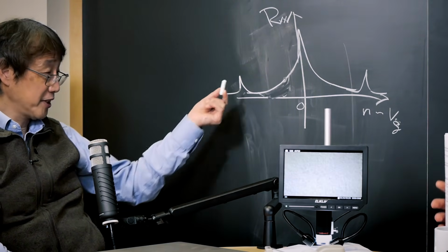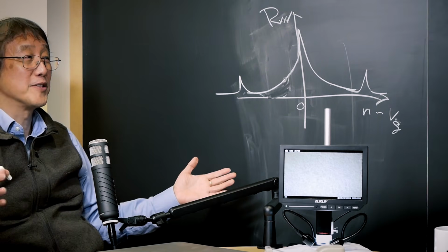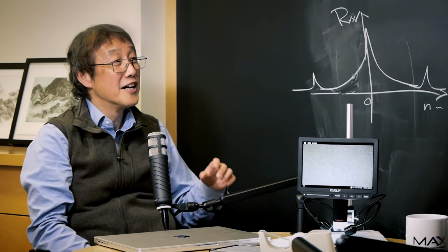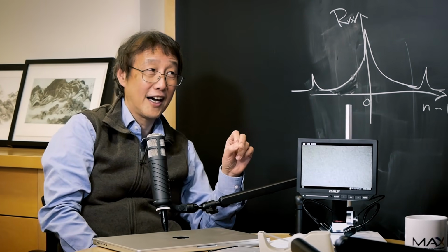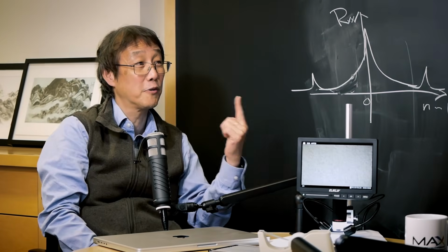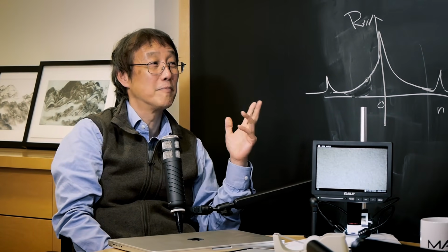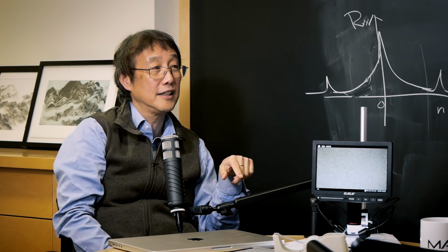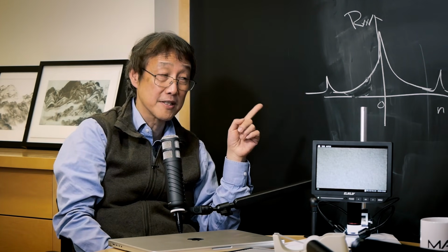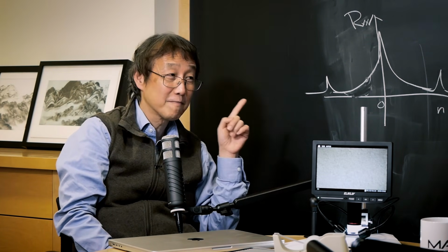But when you put this under a magnetic field and measure the quantum Hall effect, it is really complicated. Plateaus appear everywhere, and it is very difficult to figure out what is going on. So with this sort of sample, we would likely almost throw it away, until we figured out that there is not only one integer governing the quantum Hall effect, the Landau level filling. If I use two integer numbers, I can explain why the quantum Hall effect appears in this complicated way. So that is the case where we started to see that there must be something going on. And in fact, quickly we figured out that it is nothing but Hofstadter's butterfly.